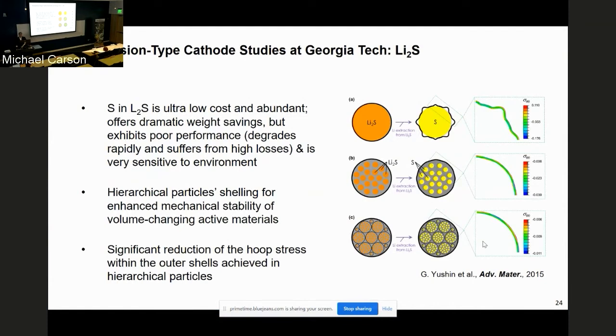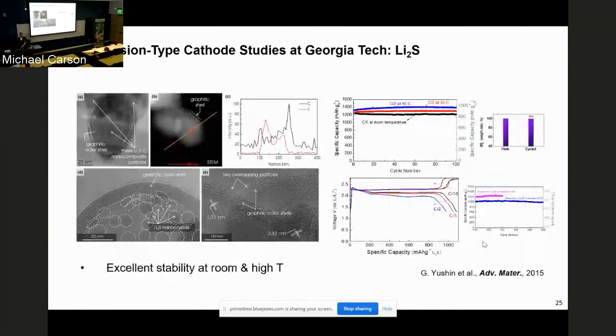And so in many cases, you have to figure out how to produce hierarchical composite particles to overcome some of these challenges. And this is one of the examples of the publications we published at Georgia Tech in 2015, again, overcoming some of these challenges. So making composite particles, small dimensions, with this core-shell architecture, where small nanoparticles of active material, in this case, lithium sulfides, are embedded in this amorphous matrix.